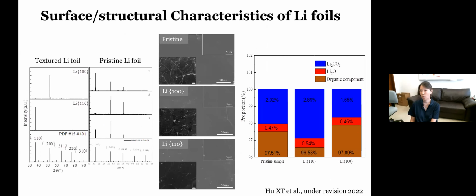Now, with that, we have three different samples. One sample is the pristine lithium that is purchased, right? And the other two samples are what we prepared. One is the lithium 100 preferential texturing, and the other is the lithium 110, right? And one interesting fact to be pointed out for the pristine lithium foil, I don't know for so many people working on the lithium metal electrode if this has been noticed. If you look at the X-ray diffraction pattern of each one of the lithium foils you work on, you will see the diffraction intensities among these peaks will be different. So there are a lot of variations in these samples, right?